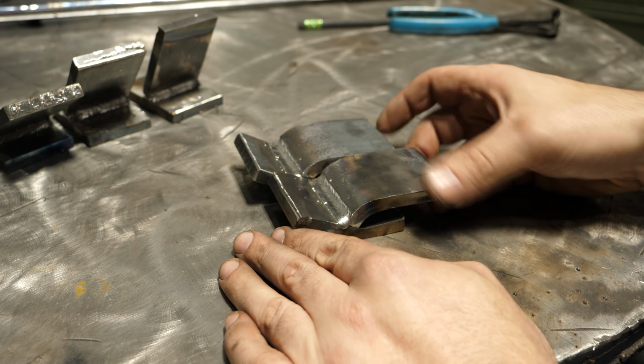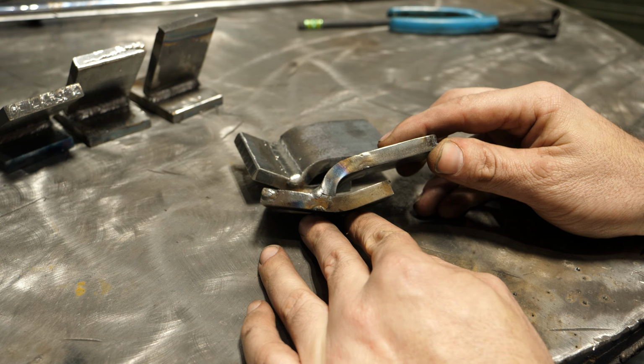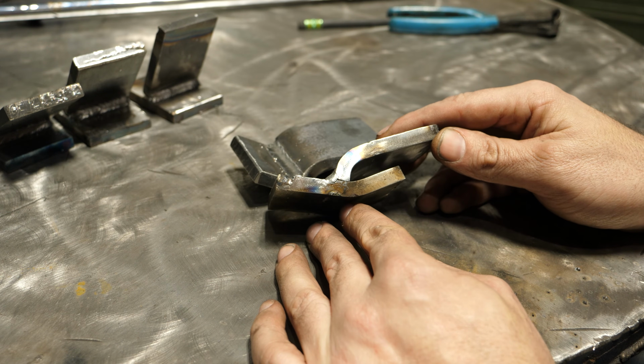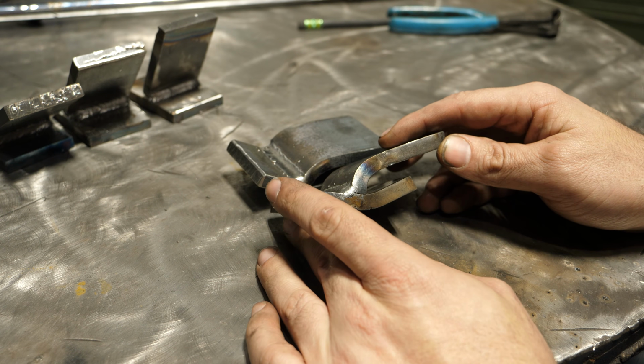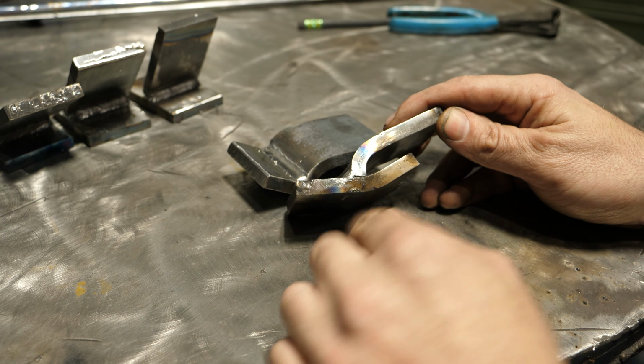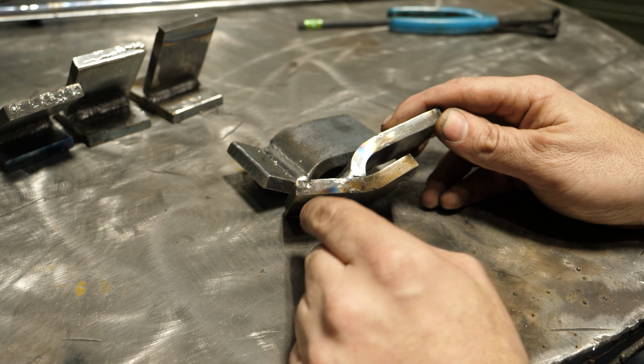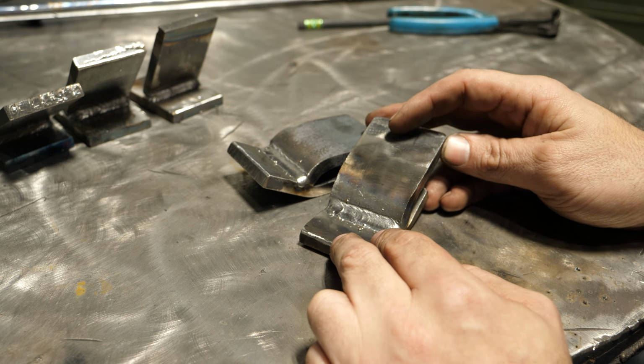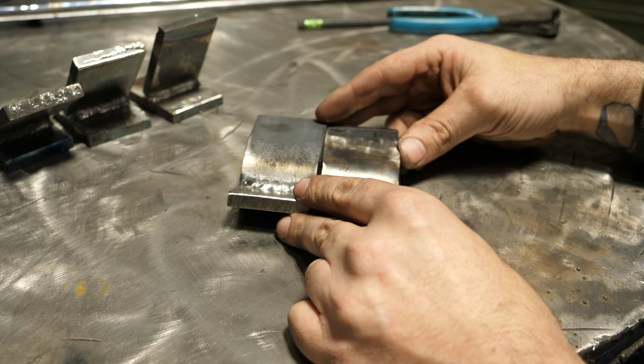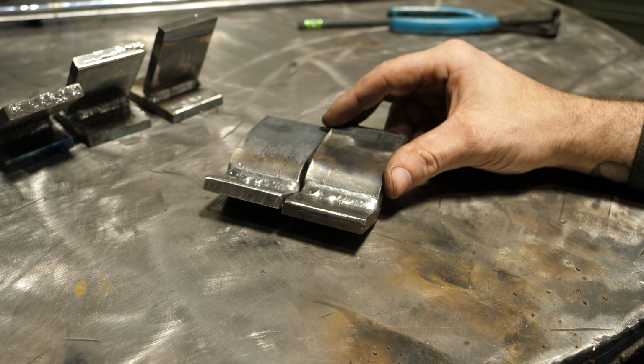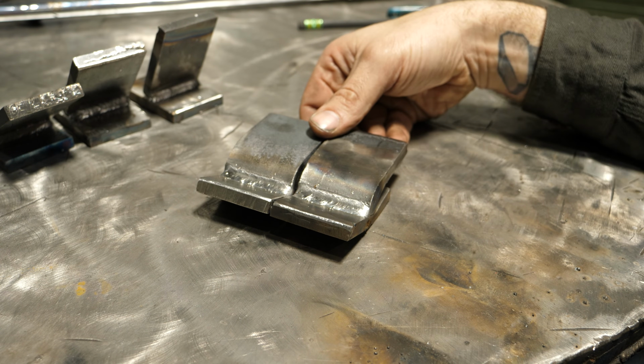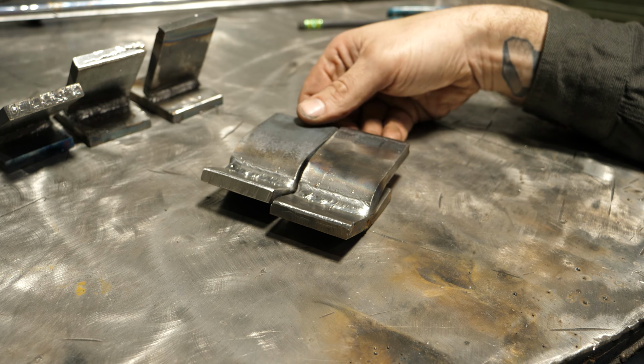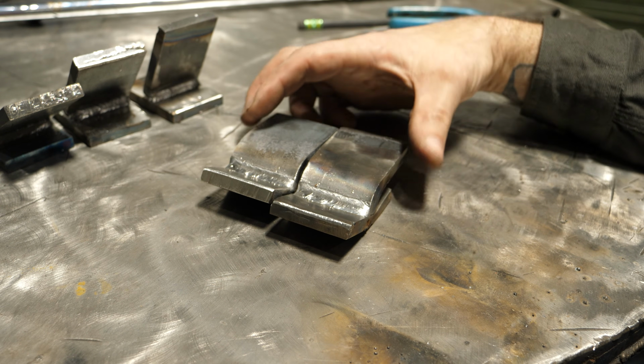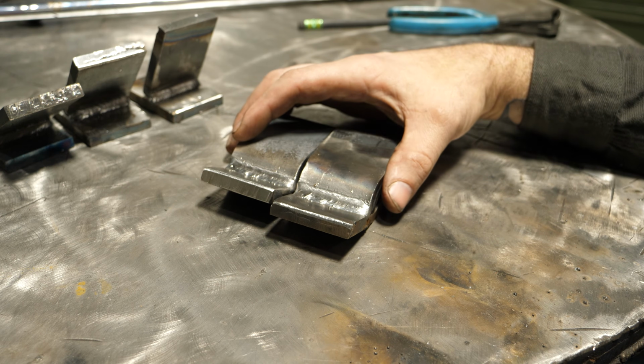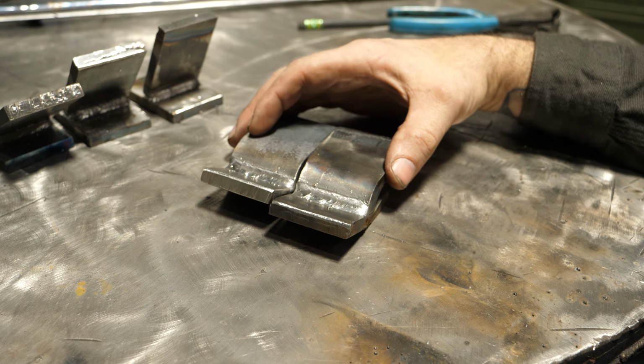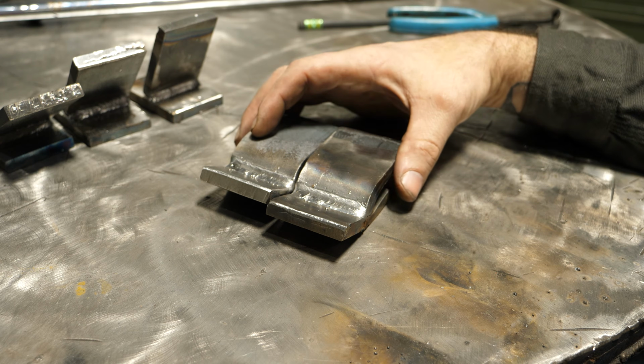And they're both bent exactly to the same size, and where it was at, I really couldn't bend it anymore. I mean, had I done any number of things to get this to not flatten out or not curve like this, I probably could have stretched the weld enough to break it. But for all practical purposes, this exceeded the strength I expected out of it, which is quite interesting. And this is a lot different, I guess, than bending it towards the face, because the face we can measure actual differences, but in the case of this, where the weld didn't fail per se, it's a lot harder.